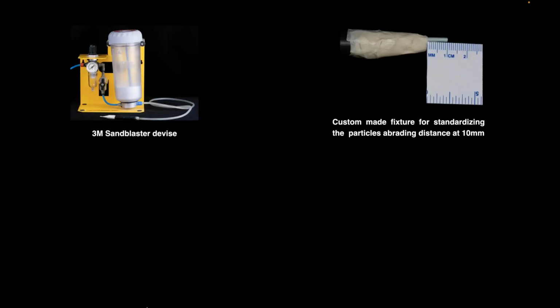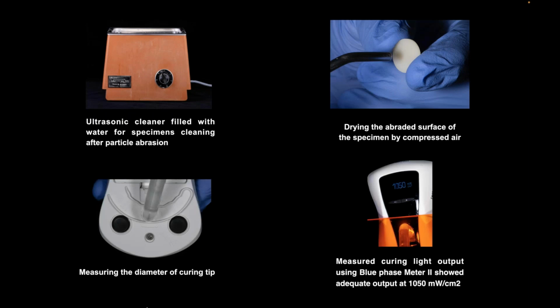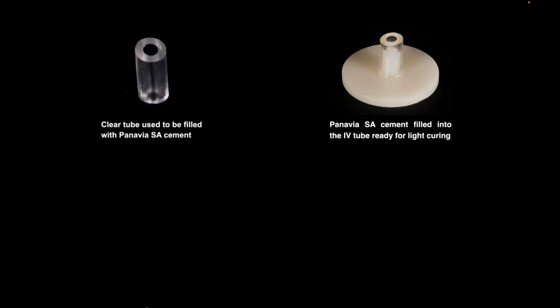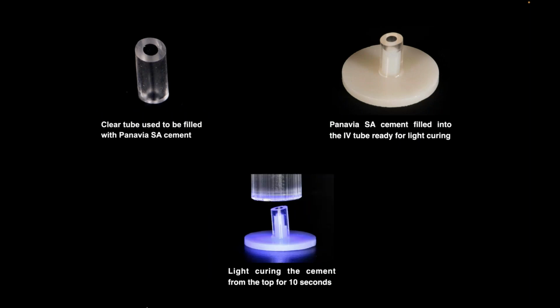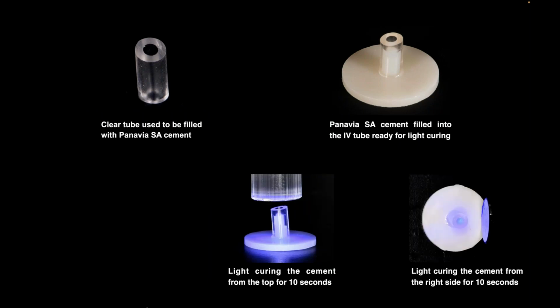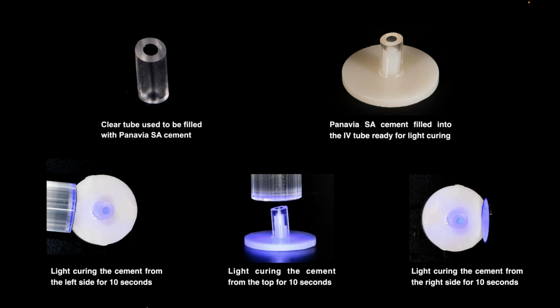The shear bond strength specimens were prepared using this 3M sandblaster device. The distance was controlled and the timing was controlled, and this last picture shows how to use that gauge, the 10 millimeter distance during particle abrasion. After that, the specimens were cleaned in an ultrasonic cleaner and completely dried with air. We measured the curing tip in order to verify the output of the curing light. We used a clear tube to fill the cement on the specimens, and the specimens were cured from the top, right, and left. The total curing time was 30 seconds. This shows the complete specimens after bonding.